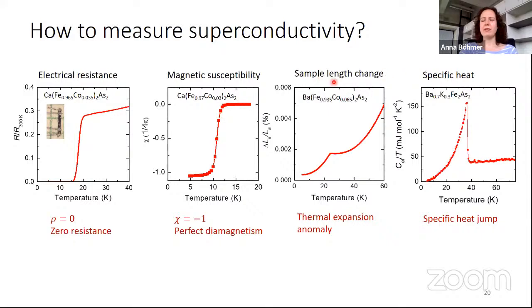One of them is the sample length change on going through a superconducting transition. So here, what I plot is, as a function of temperature, the length change of my sample. So like a piece of copper that shrinks when you cool it and expands when you heat it up. Any sample will change length when you change temperature. But when you go through a superconducting transition, and that one is here, this length change will change. So really you can see the fact that the electrons in the crystal go superconducting, lose the electrical resistance, in the sample length as a function of temperature. That's what we see here. If you think of this, it's quite amazing.